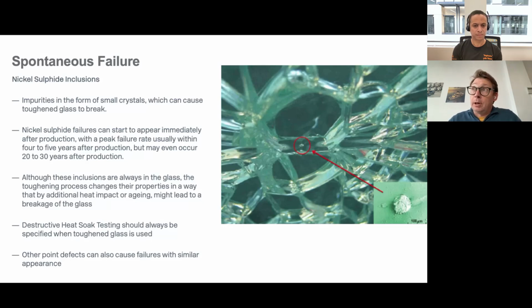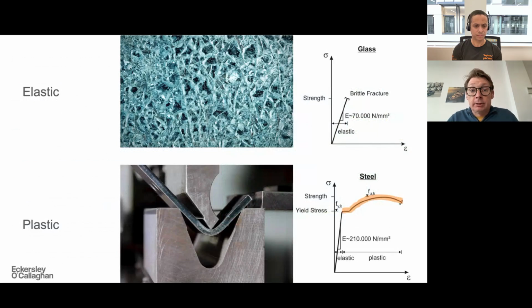So as part of being a responsible engineer, we need to look at what the consequences of a failure are. Glass is an elastic material. It has no capability for permanent deformation, and so as soon as it has reached its elastic limit, it will break. Unlike steel, which can plastically deform, and we can then see from steel structures when they start to fail. This is a particular issue in glass that we need to think about quite clearly: we have a purely elastic material, one which can fail at any particular time, whether that's due to damage or nickel sulfide.